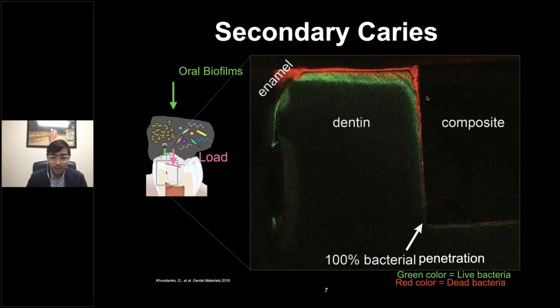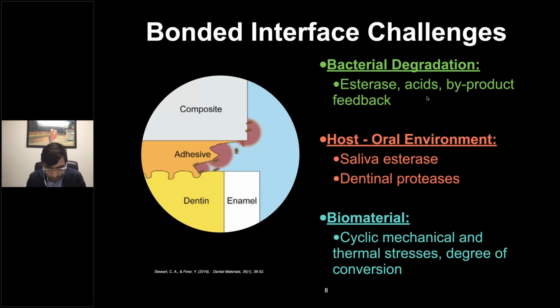So the most interesting finding about this publication back in 2016 was that they showed that the bacteria was actually able to penetrate the interface between the dentin and composite. And this is quite critical because there is no tool or hygiene technique that is able to remove the bacteria that is already implanted inside this restoration. So the idea is if we make a composite that is able to repel and kill and prevent the bacteria at that interface, then we can extend the clinical service of these restorations.